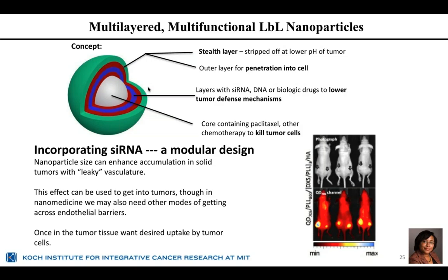And that allows these nanoparticles to essentially get into the tumor tissue and reside in that tumor tissue for some time before they find another leak to get out again. So I consider this kind of a pinball machine effect. And the idea here is that it gives us an accumulation of the nanoparticle for extended times. And here you can see these mice with tumors on their backs. And after a period of about 24 hours, we can image the quantum dot that was coated in this case and see that these nanoparticles have accumulated in these mouse tumors.